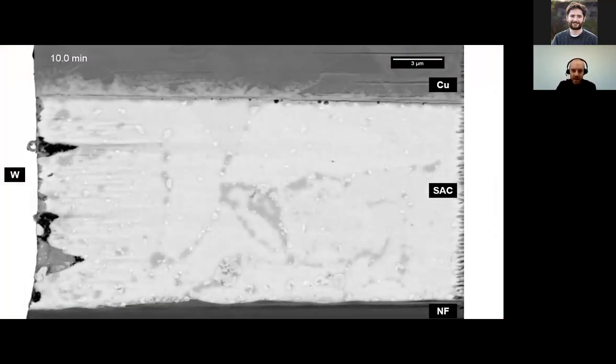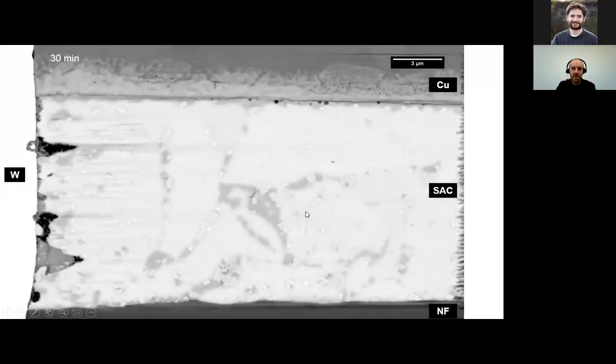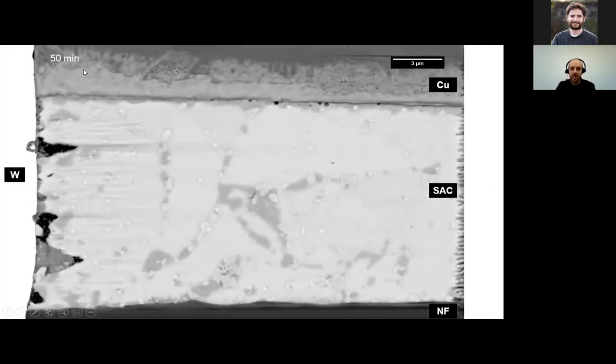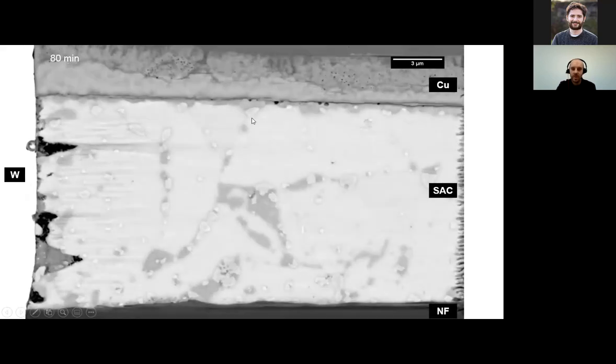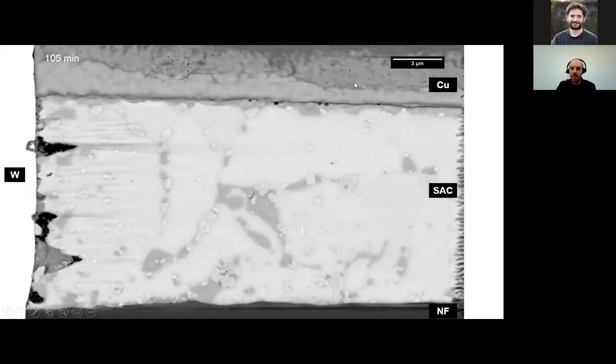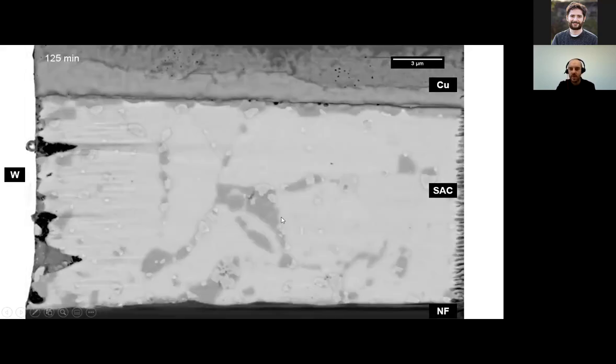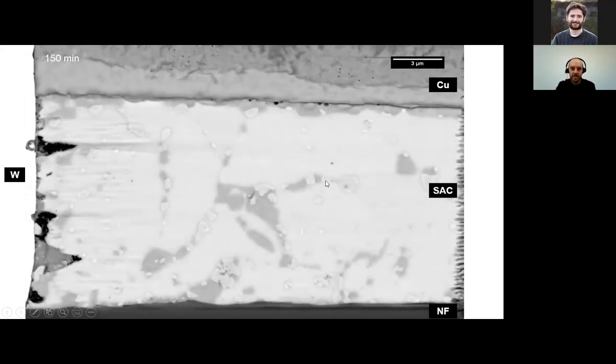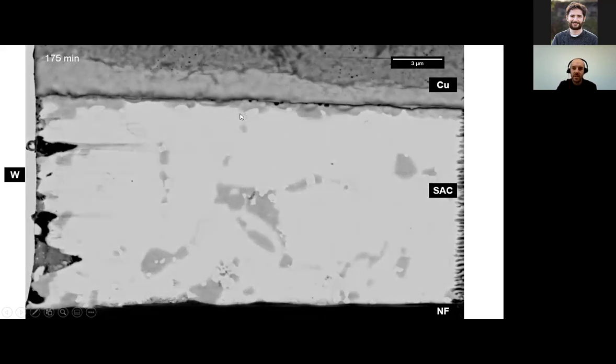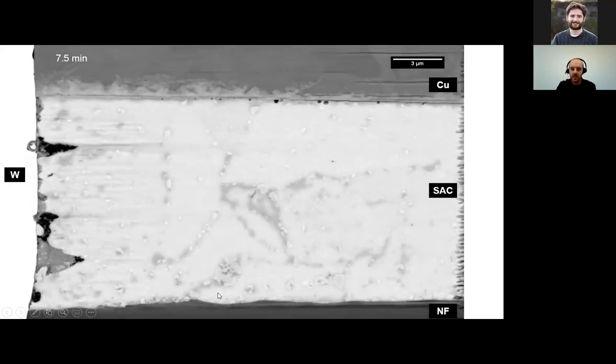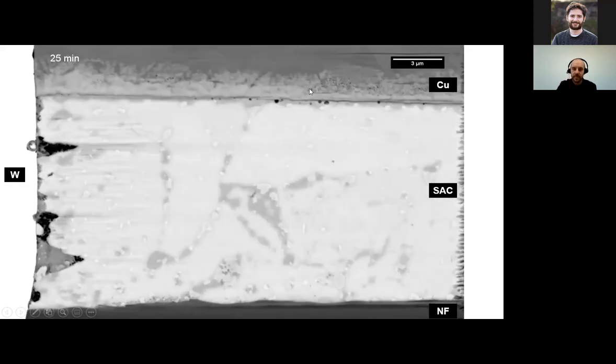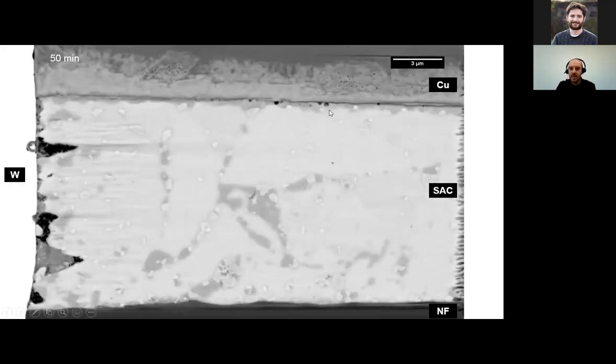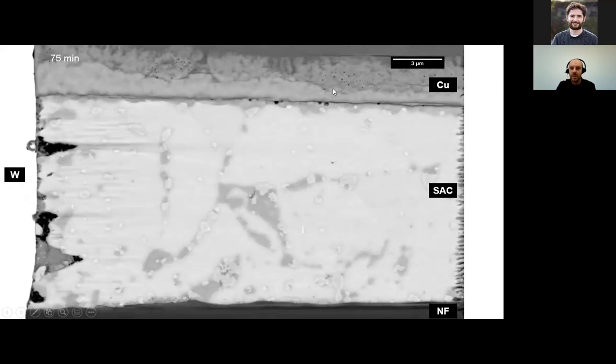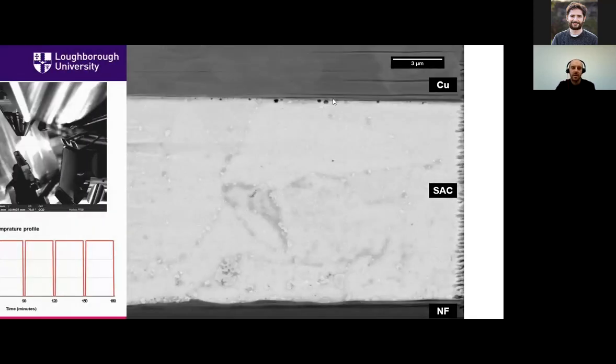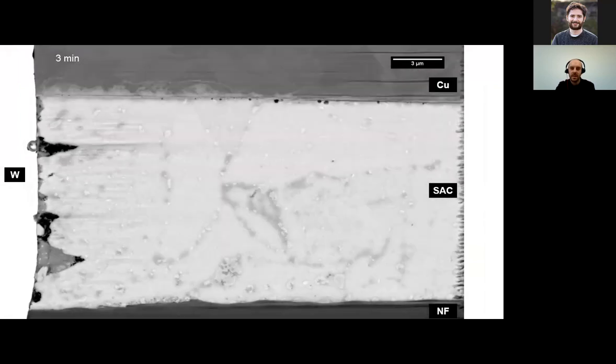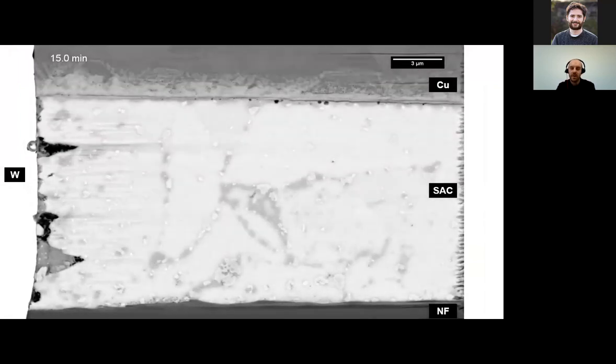So here's a backscatter image set where we're heating up the sample and aging it. You can see the time in the top left corner. And what we can see is intermetallics growing. We've got the copper at the top, the solder in the middle, and the nanofoil at the bottom, sorry. And as we heat the sample, we get intermetallics forming along that copper interface and also along the nanofoil interface. And interestingly, we can also see there's some layer starting to cover the copper sample. So if I start from the beginning again, you can see there's a layer forming across the copper.